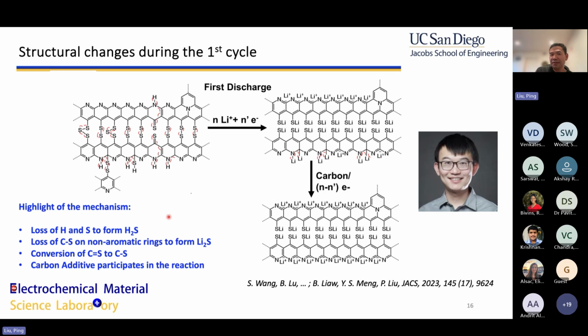Because unlike a metal oxide, the material is made by heating a polymer precursor with elemental sulfur. So we make these complex polymer-like materials. It has some electronic conductivity because there's a conjugated double bond structure. It's not crystalline, so we can't use traditional techniques like X-ray diffraction to understand its structure. It's also heterogeneous. It has a lot of different sulfur functional groups. The actual structure is more complicated than this. We're still working very hard to understand the molecular structure of these polymers and the way they react with lithium.